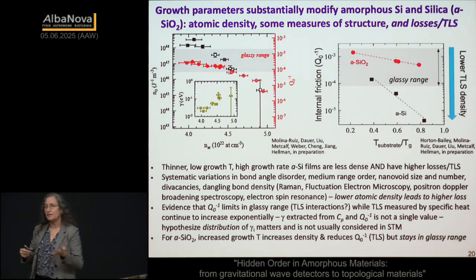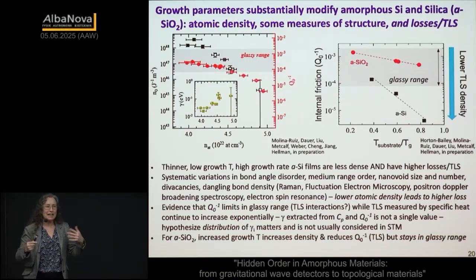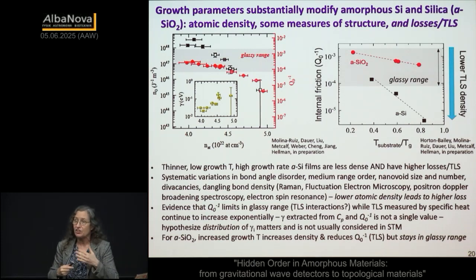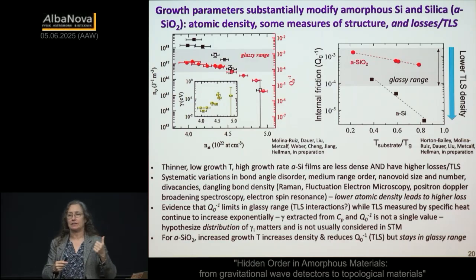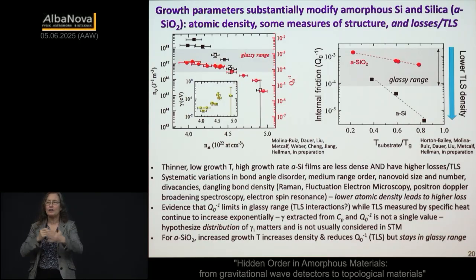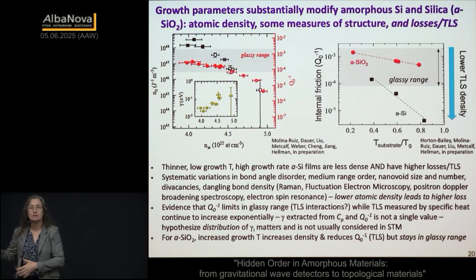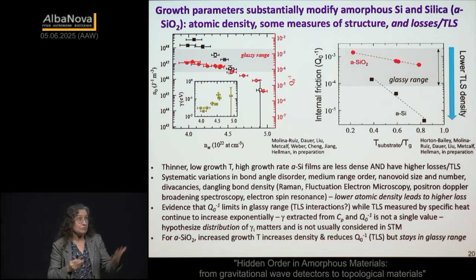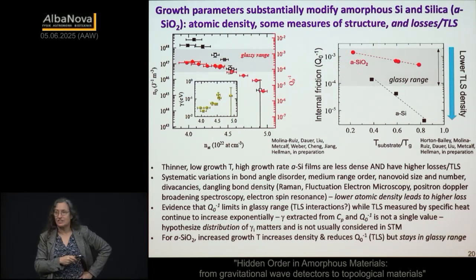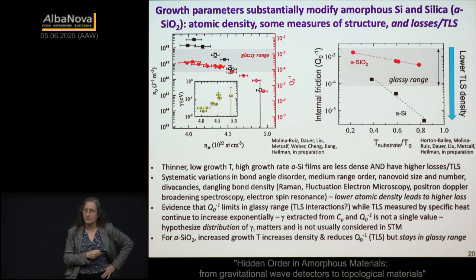Okay, and then the final comment I'll make is somebody asked me yesterday, this seems like what I'm saying is universal, like we should be able to do this with every material. In fact, my hypothesis is that what's universal about the universal glassy range is the universal nature of liquid quenching. Since all of those early samples were made by liquid quenching, the transition through the glass transition in a liquid quenching process, when normalized by the temperature at which that occurs, I believe that's the universal part. We'll see. Anyway, the point is we tried to do this with silica because we desperately need a second material that does this. And what happens with silica is all of it is in the universal range. So we failed.